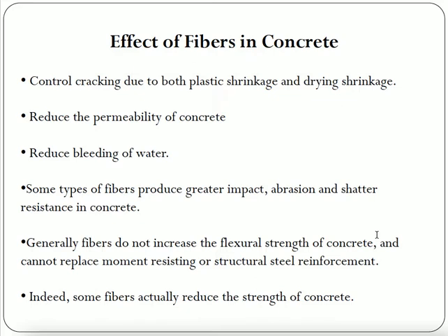Then it can also reduce the permeability of concrete and reduce the bleeding of water. Some types of fibers produce greater impact, abrasion, and shatter resistance in concrete, because they are microfibers, so they can offer better impact resistance to the concrete material. Generally, fibers do not increase the flexural strength of concrete and cannot replace moment-resisting or structural steel reinforcement. However, some fibers actually reduce the strength of concrete.